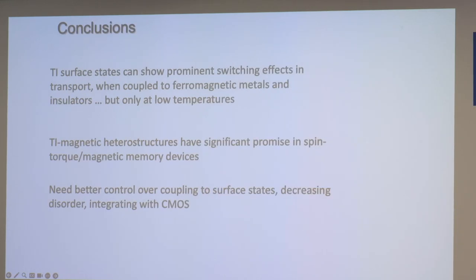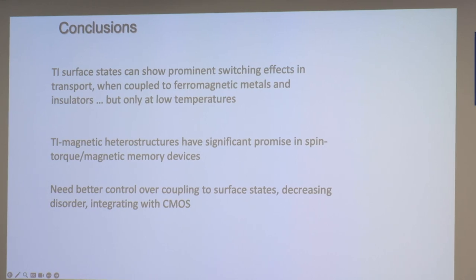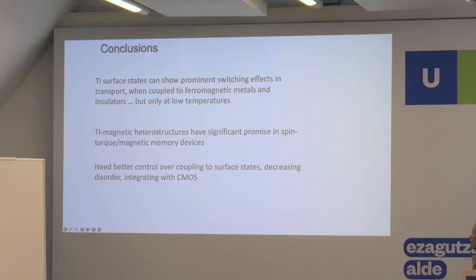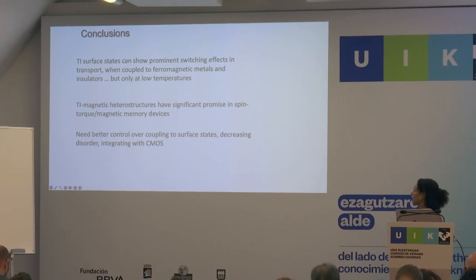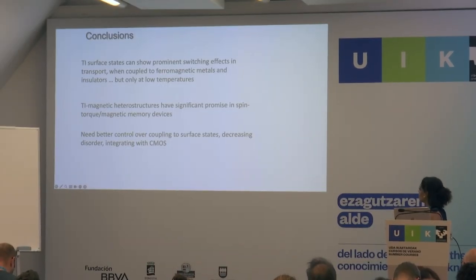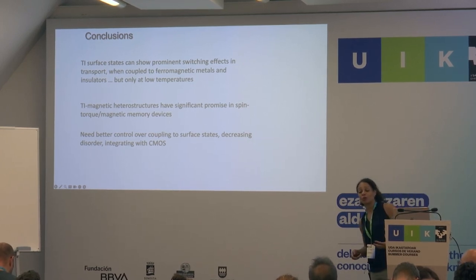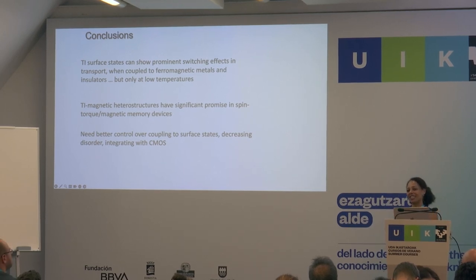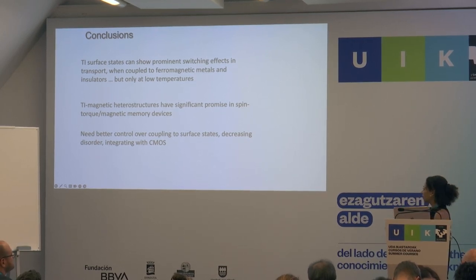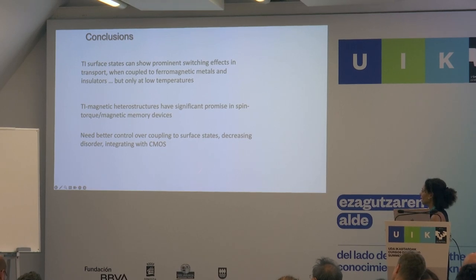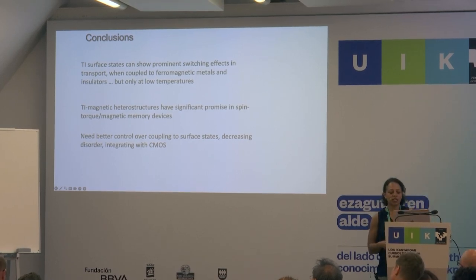Okay, so in conclusion for today's talk, we have these surface states that can show these prominent switching effects when coupled to ferromagnets, metals and insulators, but only at low temperatures. Again, I don't know what sets the temperature scale, but it's definitely there. These TI magnetic heterostructures do seem to have significant promise in spin torque magnetic memory devices, but more work needs to be done to understand exactly what that coupling is and to control it, especially that proximity coupling. And we just need better control over this coupling to surface states, decreasing disorder and increasing compatibility with CMOS before we can move on to anything that's practical, or even before we can study these effects in more detail.